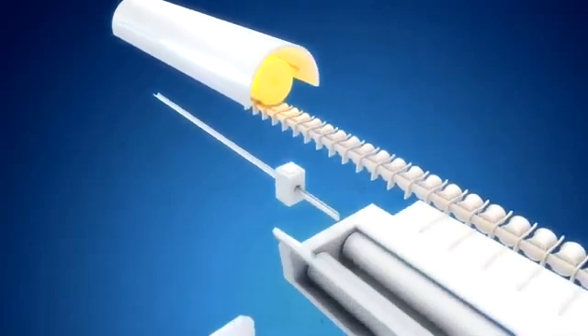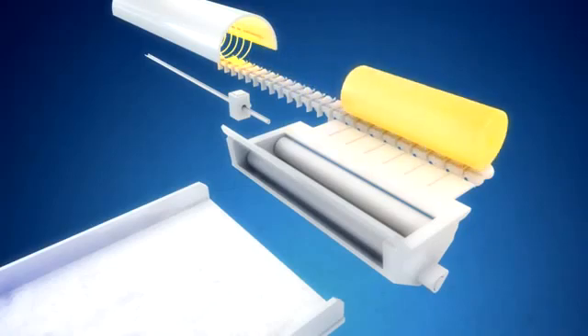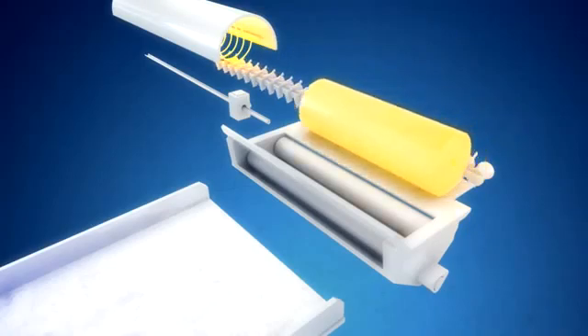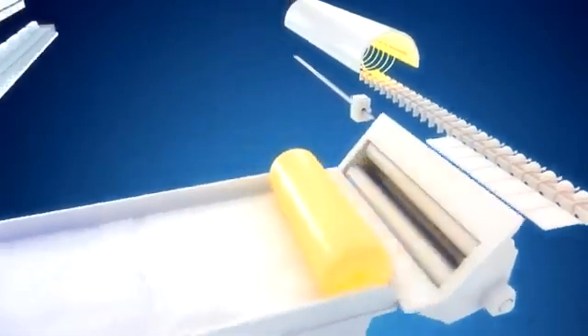The extrusion billet is heated to about 1200 degrees centigrade, and then lubricated internally as well as externally with a glass powder.